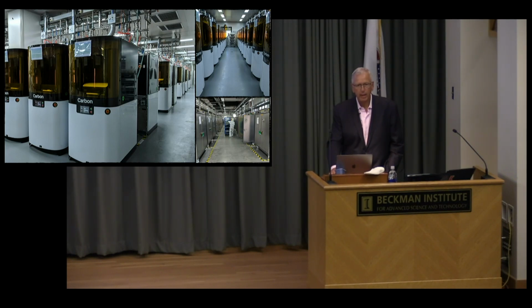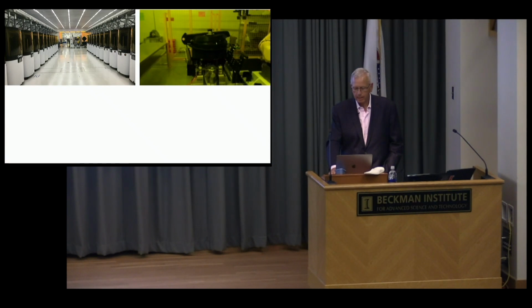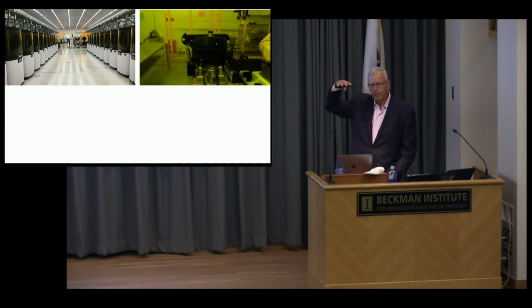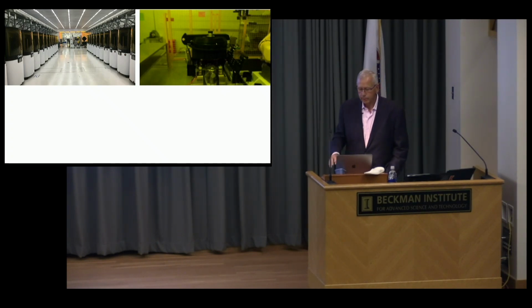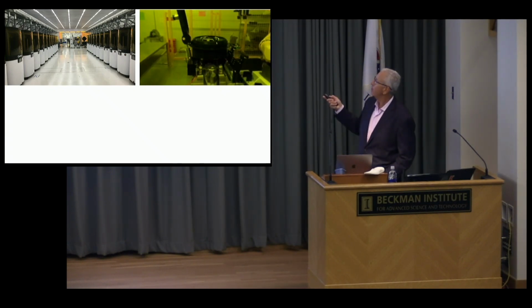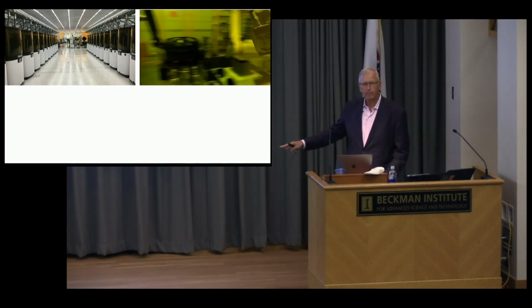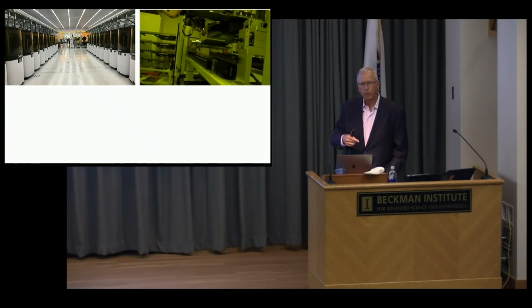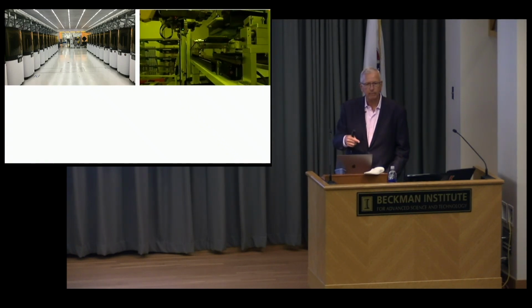This is our factory in Shanghai. And then, when you print a part and it's got excess resin on it as it's printing, and I'll show you the chemistries here in a little bit, you want to get that excess resin off. You can't afford to wash things at this scale. So we developed basically a salad spinner. You'll see a platform, a robot will come in and grab it. You'll see a pair of shoes. It goes around in a centrifuge, and that excess resin is flung off, collected at the bottom, and goes back into the printer. So there's no waste, and there's no mixed waste generated with solvent.